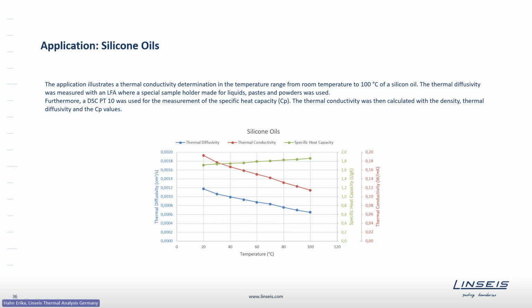And here a second example of a liquid measurement. Here we tested a silicon oil up to 100 degrees Celsius and combined the data of thermal diffusivity with specific heat capacity measurements done by a DSC. In the end, we could calculate the thermal conductivity. So that just illustrates a little bit the application range.